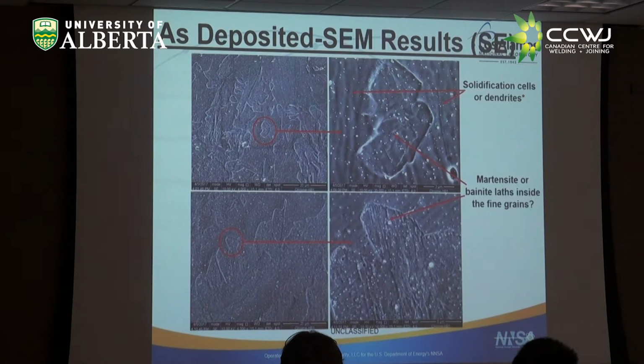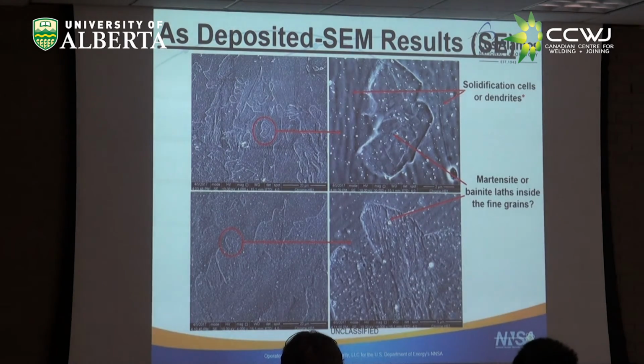When we first saw these opticals, we were looking for martensite, which has a completely different microstructure, and this was all a big surprise. Did we buy the wrong powder, or are we just like the first people in history that can't make martensite properly, or what's going on? At this point we were very confused. We look in the SEM and we see stuff at higher mag that looks a lot the same, except we can see some of these other things here.